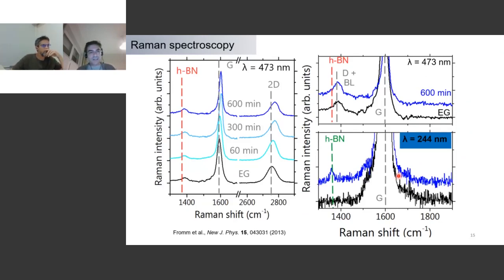And it's not so easy in this case to observe hBN formation. One of the reasons is that we do have a peak here, exactly where the hBN signal should appear in Raman, that overlaps with it. This is due to the D peak that we have in graphene. So we do always have some defects, and it appears here. And on top of that, we know, from a previous study, that the buffer layer itself has a Raman signal that consists of a very broad band exactly around this area. That's why I write here D plus BL, that is for buffer layer.